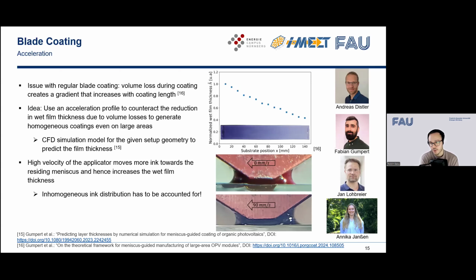On large areas, we usually have a volume loss at some point because we use small amounts, only 55 microliters. And if we coat along, we lose volume. A loss in volume means that we end up with thinner wet films and thinner dry films. To counteract that, we can use acceleration because, as we learned, the faster we go, the thicker we get. To balance that off, we used CFD simulations to find out how we have to adjust our acceleration profiles to get homogeneous layers.